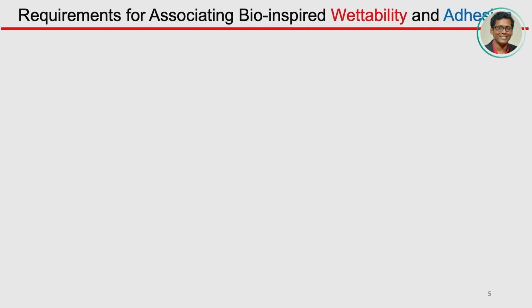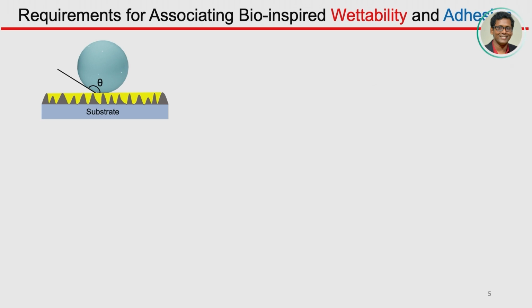But that is just the criteria, right? To understand what's going on, people did a lot of study and figured out that when you talk about such extreme liquid wettability, whether it is water or other liquids like oil or low surface tension liquids, the important parameter is the third phase, which minimizes the contact between the beaded liquid and the solid surfaces. So this yellow color is basically indicating that external third phase. If it is super hydrophobic, that external third phase will be here.